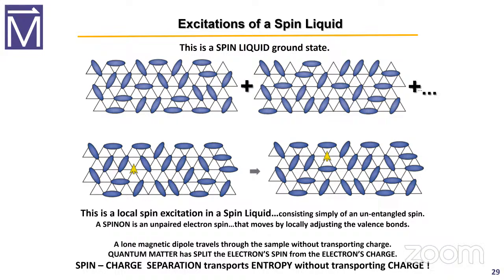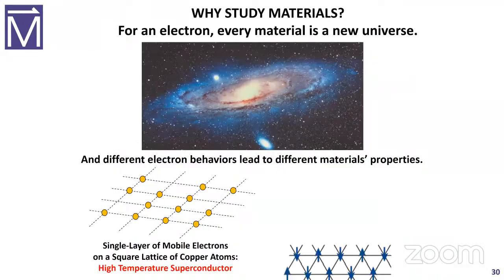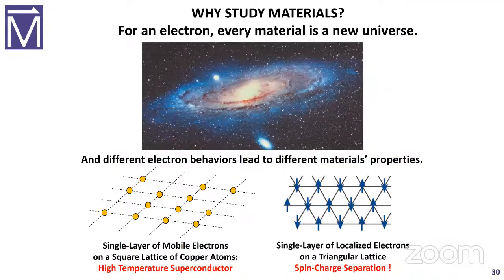Quantum matter has split the electron's spin from the electron's charge, the two properties of an electron, and you've separated them in this material. Spin charge separation transports entropy because you can move these magnetic moments without transporting charge. So the answer to our question before is if you go from square lattice to triangular, you go from high temperature superconductor to spin charge separation. Incredibly exotic properties in a material that are just driven by geometry in this case.